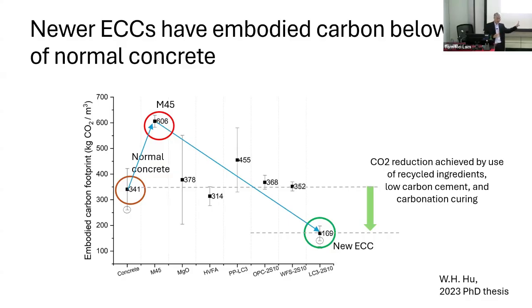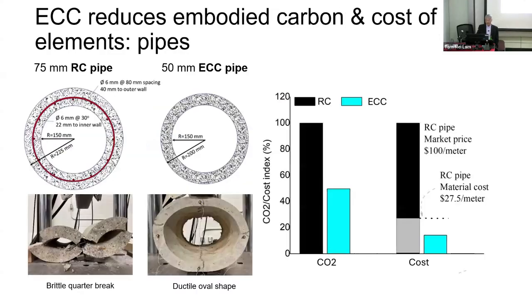But for some time, that was the only low carbon binder available. On my last visit a few months back in mainland China, two of my former students have started companies, developed and commercialized low carbon binders based on waste material. These are already available now. So low carbon binder is used, some of the ingredients are recycled, and carbonation curing is also used during the hardening stage of the ECC material. When you combine all those, it's possible to drive down the carbon footprint. So this is the embodied carbon of the ECC material at the beginning stage of the service life.